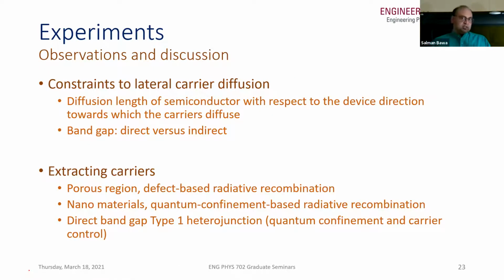So what are the constraints to lateral carrier diffusion? The first is the diffusion length of the semiconductor with respect to the device dimension, particularly the direction of the device in which these carriers diffuse. So the diffusion length is important. If the device is too wide, the carriers would just annihilate in the device and would not reach the defect centers that we have created. Another is band gap. So if it's indirect band gap, it would encourage the carriers to transport, as compared to direct band gap, where the carriers would have a higher probability to radiatively recombine rather than diffuse.